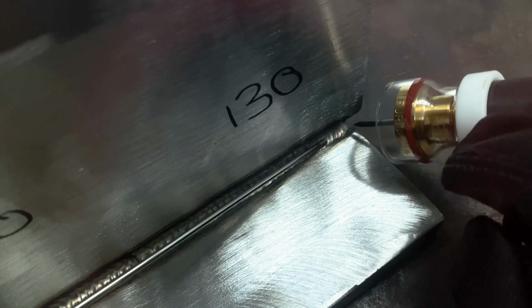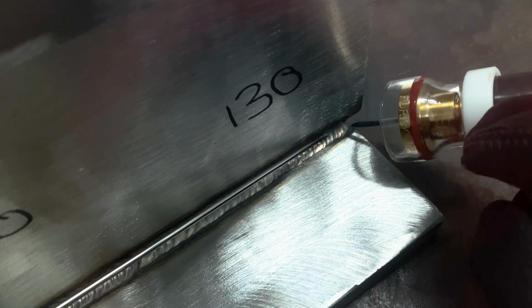All right, coming back in for the second pass, using the same amperage respectively, we're going to use a lay wire technique instead of the dip like we did before. And again, you'll notice a trend here, right? My amperage is sufficient enough to melt everything together to make that perfect marriage that we're wanting, but my travel speed's slow. I'm having to really wait and concentrate and tie in the sides.